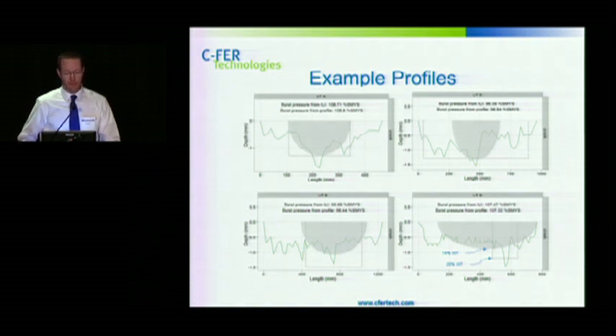The interesting case on the bottom right is one in which the feature is very long and it is also very shallow. So it is just under the threshold where the tool claims to be able to find these features. And so for that portion of the feature, it didn't call anything, but as soon as the feature dips down below that threshold, it does find that portion. But because this is connected to that long, shallow portion, this is one of the non-conservative calls. In this particular case, it works out to about 107% of SMYS.